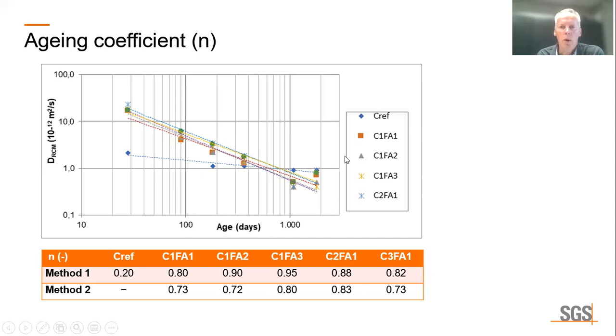And if we now derive the aging coefficients from the slope of these curves, we see that the fly ash mixes have values between 0.8 and 0.95, and these values are much higher than that of the reference concrete.